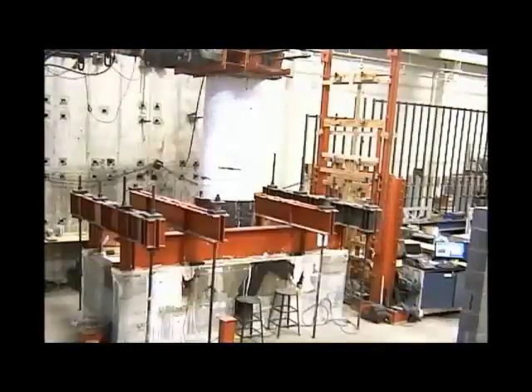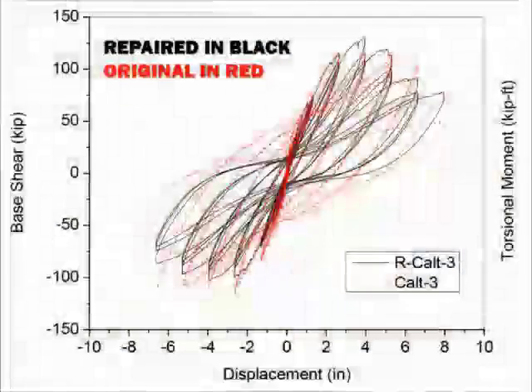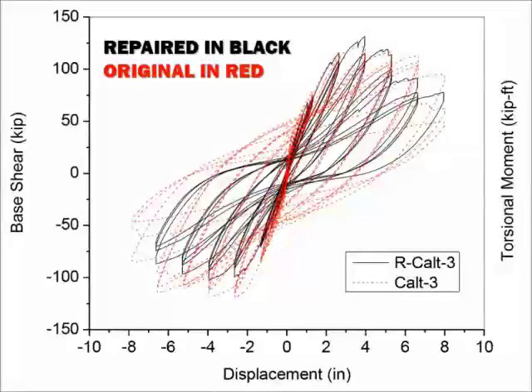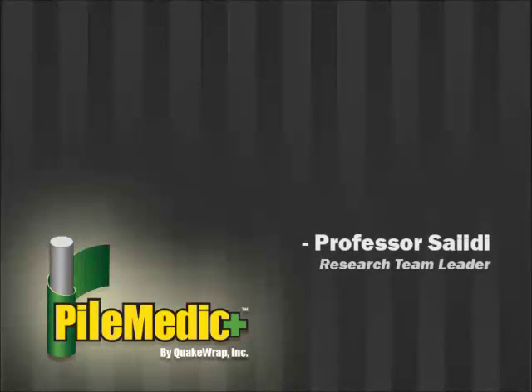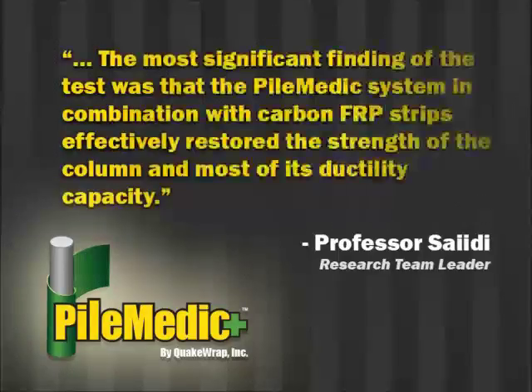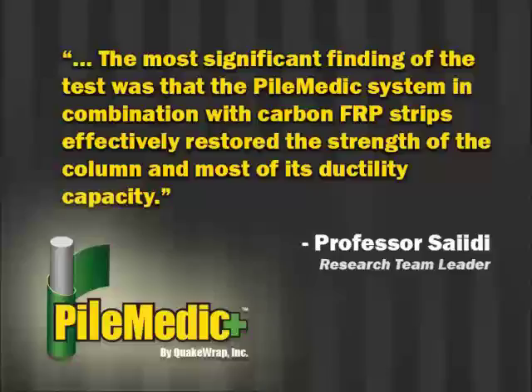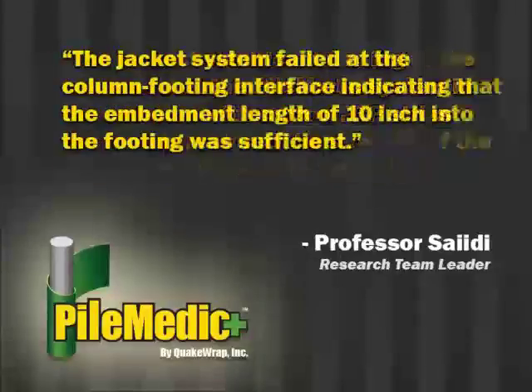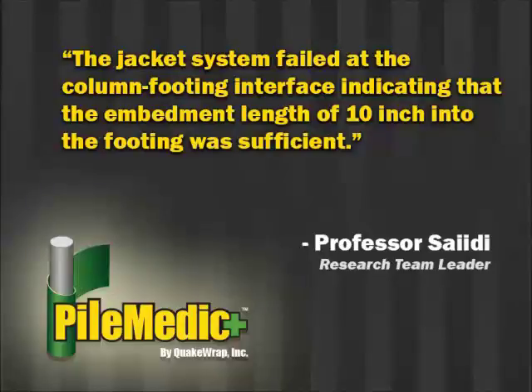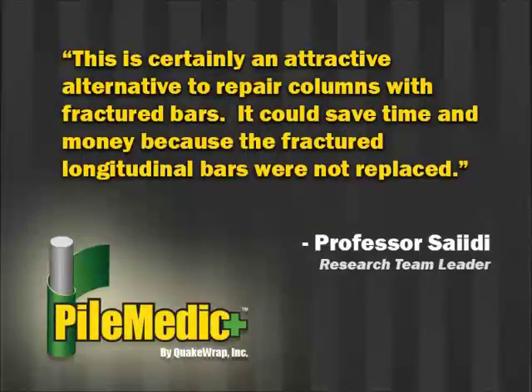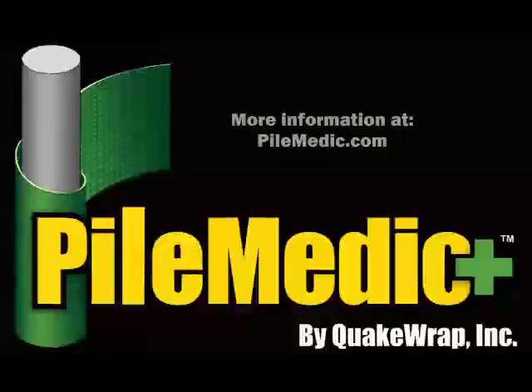The repaired column was subjected to reversed cyclic loading. The load deformation hysteretic response of the original column, shown in red, can be compared with the repaired and strengthened column, shown in black color. The research team leader, Professor Saiidi's comments to the Caltrans engineer are quoted below. The most significant finding of the test was that the PileMedic system, in combination with carbon FRP strips, effectively restored the strength of the column and most of its ductility capacity. The jacket system failed at the column footing interface, indicating that the embedment length of 10 inch into the footing was sufficient. This is certainly an attractive alternative to repair columns with fractured bars. It could save time and money because the fractured longitudinal bars were not replaced. Please visit our YouTube channel for more videos of our products.